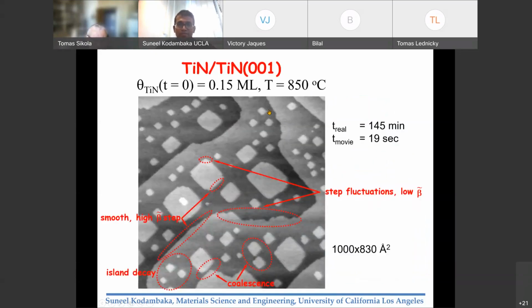So the experiments we did is to first deposit epitaxial titanium nitride thin film on single crystal MgO substrate, and all the images you will see will be titanium nitride surfaces. And the 2 orientations we have studied are titanium nitride 111 films that were grown on either MgO 111 or on Sapphire 0001, or titanium nitride 001 oriented films that are heteroepitaxially grown on MgO 001.